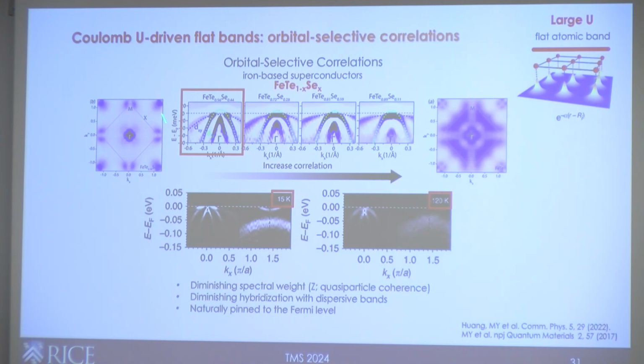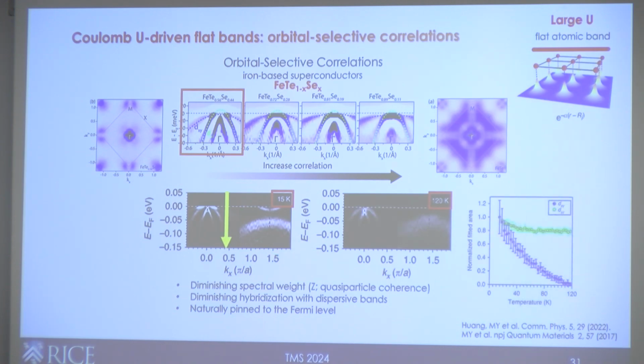So if you take one of these guys over here, which is shown here, if you crank up the temperature, this faint band actually disappears. All of its quasi-particles disappear from near the Fermi level, along with the hybridization with the dispersive state. Without going into too much detail, you can track how this spectral weight disappears, and this tells you that as a function of temperature, the quasi-particle of that orbital goes away, right?